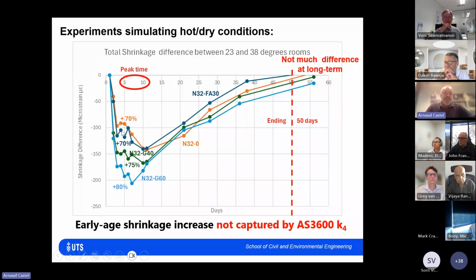Not much difference depending on the binder composition. It's a 70 to 80% increase in shrinkage, which is a lot of difference. At long term, past 50 days, not much difference anymore. All the shrinkage results are merging together more or less.